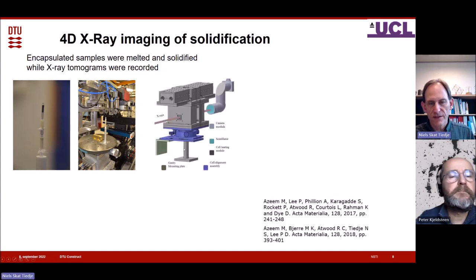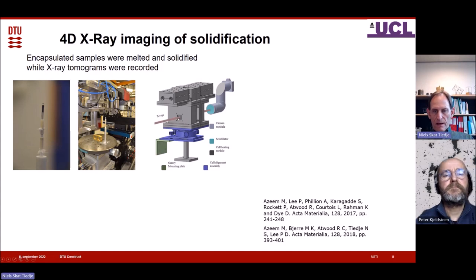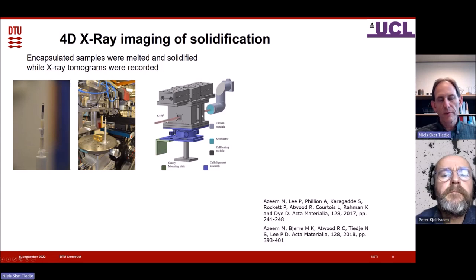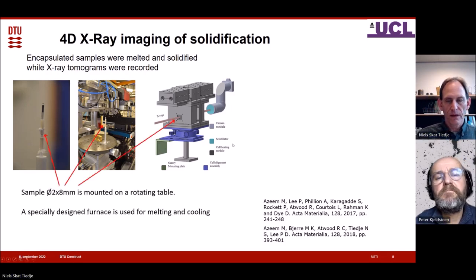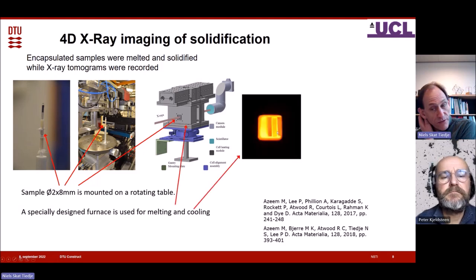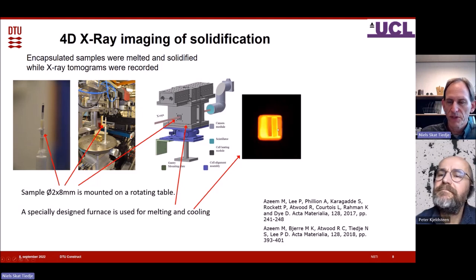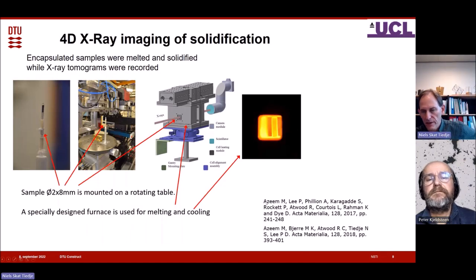You can see the sample here. This is the sample holder, the furnace. X-rays coming in, goes through the sample. Hang on, it comes the other way. The X-rays come from left to right, and then we have the detector here. So we make basically 2D images. But when the sample rotates, every time you have a bit of rotation, you take a new picture, and then you build up a 3D structure like this. You can see the sample inside the furnace. And we can heat to 1400 degrees in this one, which is much more than we need for cast iron.